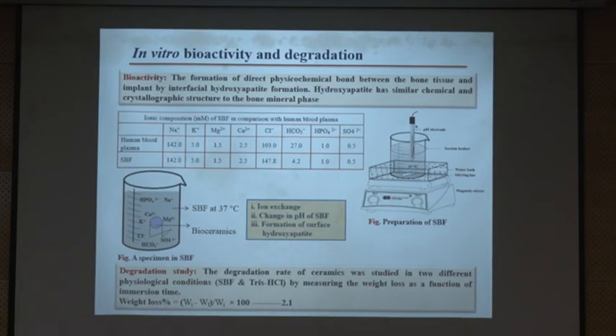So what we are going to do here is prepare the sample, make it a pellet, and then immerse the pellet into the SBF, simulated body fluid. After 3 days, 7 days, 14 days, or 28 days, whatever the duration of time, we are going to remove the sample and check it out. We are going to characterize before immersion, and we are going to characterize after immersion.